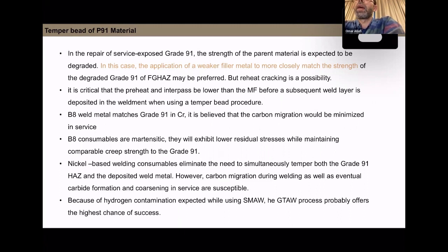So it is critical also that preheat and interpass temperature be lower than the martensitic formation. So this material is martensitic steel. Normally during welding, you preheat, you weld, then you apply post heating, then you cool it down before doing PWHT. Why do we cool it down? To ensure that the martensite is fully transformed before doing PWHT. So this is critical. That's why you need to keep the preheat below the martensitic formation temperature, which is around 160. That's why the preheat temperature usually is 150.